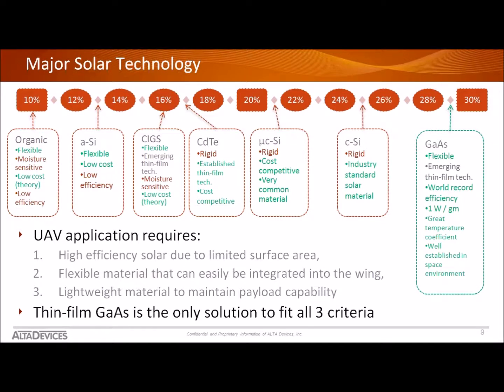Then we come up into our mid-range efficiency, but we're starting to get into more rigid solar material. So the bulk of your higher or mid-range efficiency material is all rigid. And then gallium arsenide sits higher than silicon, which is our industry standard, up around 29%, or 28.8% efficient is our record.